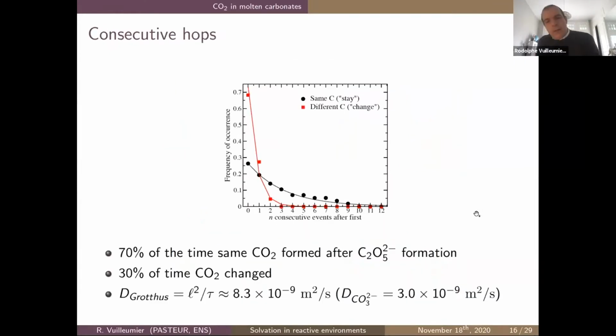We could not really compute the diffusion coefficient yet. It would need much larger simulations. Somehow it would be a waste of time. We could look at the statistics of the hops, and from the statistics of the hops you can build a model for the diffusion coefficient, which we estimate to be about 3 times the diffusion coefficient of the carbonate ions themselves. So this remains to be seen experimentally.